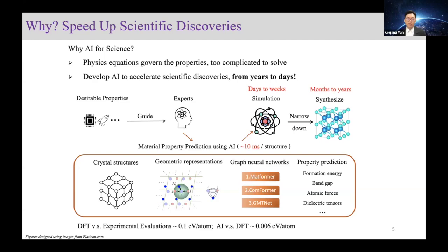Additionally speaking, the reason that we can replace density functional theory calculations with AI algorithms is because of the accuracy. When comparing density functional theory calculations with experimental verifications, the error range is around 0.1 eV per atom for the energy. And for the error between our developed AI algorithms and the density functional theory ground truth, we can achieve around 0.006 error. With this comparison, we can see that if we directly replace density functional theory with AI algorithms, we are only adding a small variance to the density functional theory predictions, but bringing more than 5 magnitude speed up over the traditional methods.